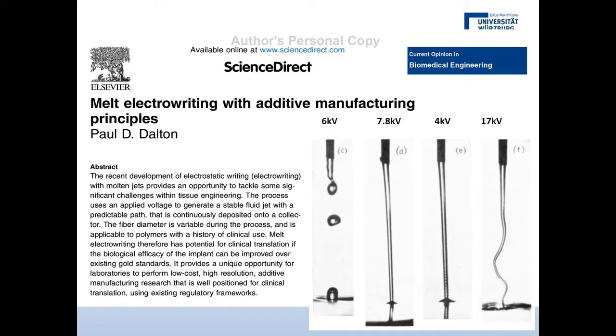Because when you charge a fluid, all the charges go around the surface. And so it's now a very, very strong structure that doesn't undergo perturbations and doesn't go through droplet breakup. So in a way, the reason we apply voltages is to prevent droplet breakup. And there's recent papers showing that you can apply as little as 100 volt, 200 volt to a polymer solution and maintain this jetting phenomena.